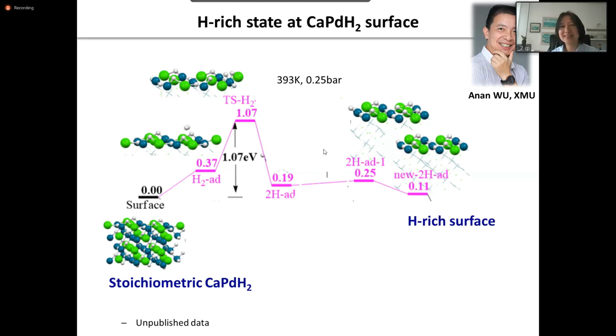So these results remind us that the hydrogen at the surface could be more than we expect, because in heterogeneous catalysis in our field, people all know that there is hydride on the surface, but it's very difficult to identify the hydrogen content, hydrogen species, and hydrogen chemical environment. However, there are many unknown things, which means that we can explore more.